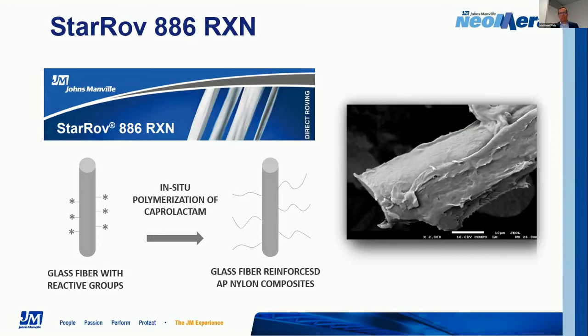And this particular sizing development was designed around the use in AP nylon systems. And what we did is develop a sizing that had reactive groups on the surface of the glass to help promote polymerization at the glass surface. And that obviously promotes the polymerization process, but also the bonding and the strength of the interface between the fiber and the matrix. And so what you would get is the nylon would grow off of that surface, and you get a very strong bond.